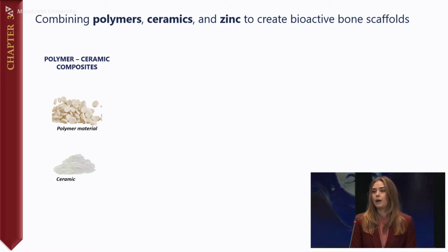We started by combining two very well-known synthetic materials, polymers that are known to be very flexible and easy to shape, with ceramics that are known to stimulate bone growth. Alone, each of them has weaknesses. Polymers don't interact with cells very well, while ceramics are brittle. But by combining them together, we can get the best of both. We get structure and we get bioactivity.